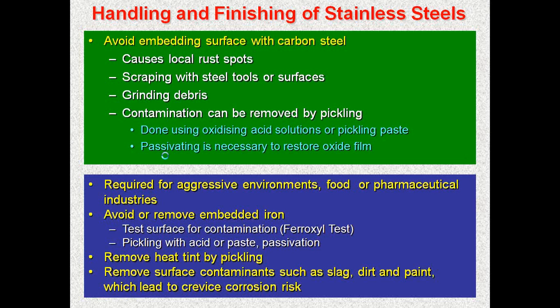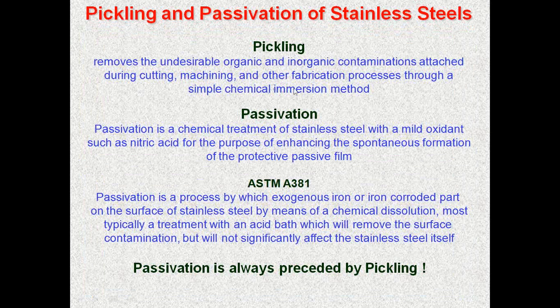Pickling and passivation is well known to all of you. Pickling is a descaling process using chemicals like acids, and passivation is again a treatment to form an artificial oxide film on the surface. Particularly it is done with a mild oxidizing acid like 10 or 20% nitric acid. There is an ASTM process, and this never ends with only pickling. You should always follow with passivation. And for every component, when it arrives at your industry, you have to ensure with your fabricator that the final step is pickling and passivation, or before you put the component into final use, you must ensure that they are always pickled and passivated.